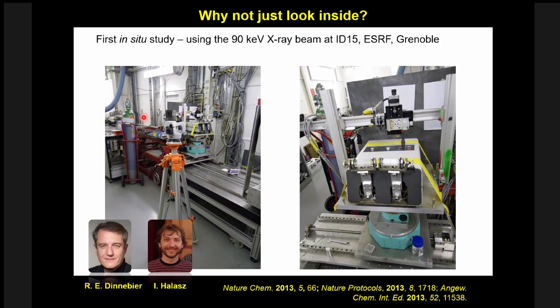And you're starting to see that the composition of your milling mixture, if you're observing it in real time, is very different than what you get by stopping the reaction, sampling it out, and measuring, and so on. For example, we see the appearance of phases that you normally don't observe because they last maybe only a few minutes. So now you know that they're there.